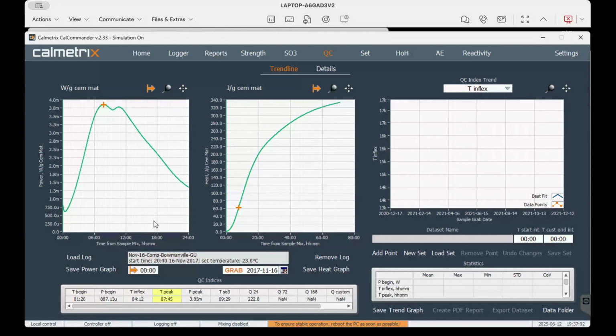Sometimes the software can actually go wrong if there's lots of peaks. It can select the wrong peak. You could actually move this manually if you wanted to. But in general, the software is quite good. It's mathematical. It's quite good finding where those peaks are and those things. The power of the peak, and then where the sulfate depletion occurs, and then on the right-hand curve at 24 hours, what the total heat is.